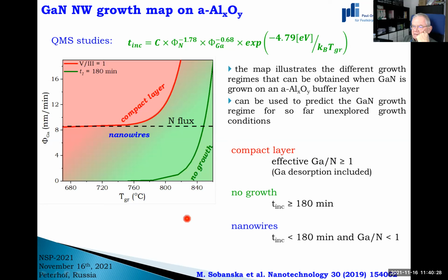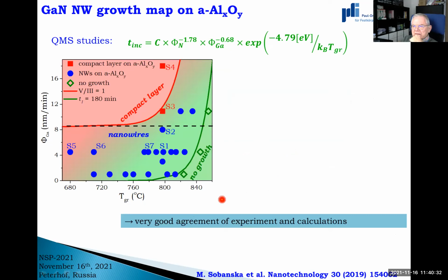Okay, and now let's try to compare this with experiment. We grew several samples, and these 3 green points are nanowires for which incubation time was much longer than the 180 minutes that we declared here. These 2 red squares are compact layers, as we have seen from some images, because of course after each growth we studied the surface using scanning electron microscope. And all this blue inside are nanowires, as also seen in some images. So we have a very good agreement between experimental data and our expectation from calculation.